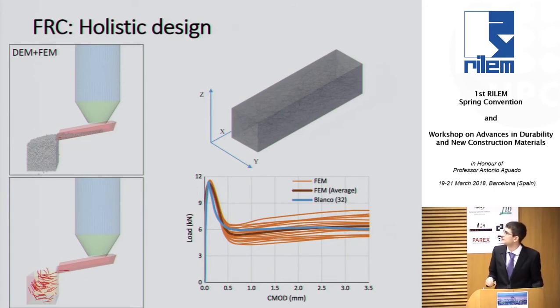Right? So we have optimized this. And we can obtain results as you see here. This is the crack opening of the element. This is the load applied. And you see the blue line is one of the experimental results. And what you see in the other curves here, all of those are the result of different simulations using the same condition.